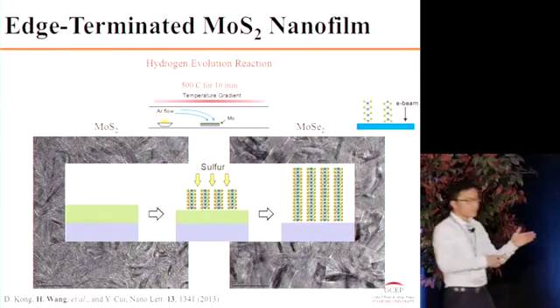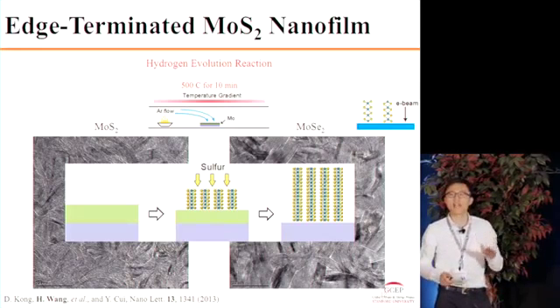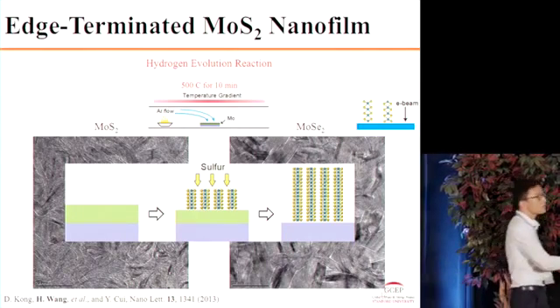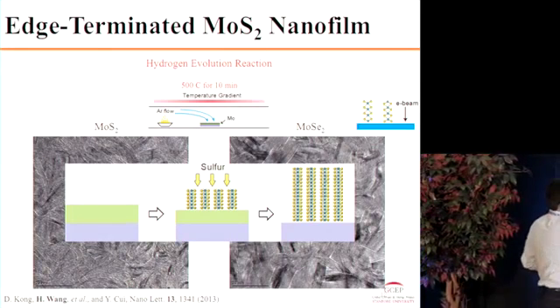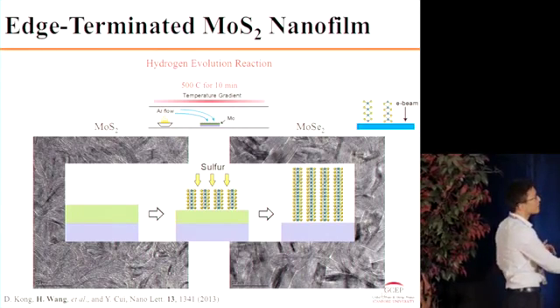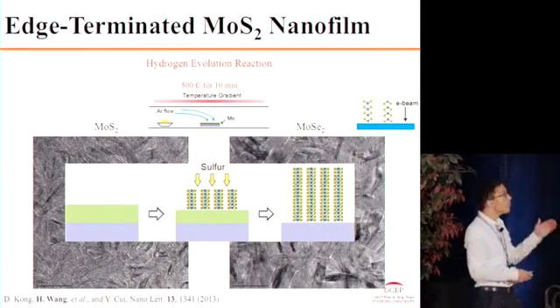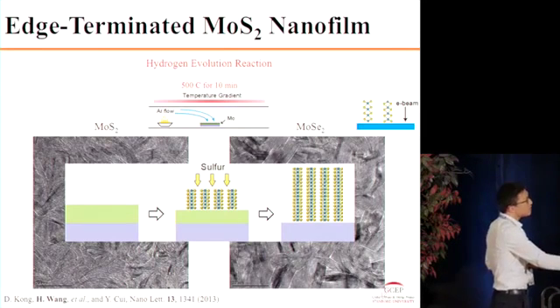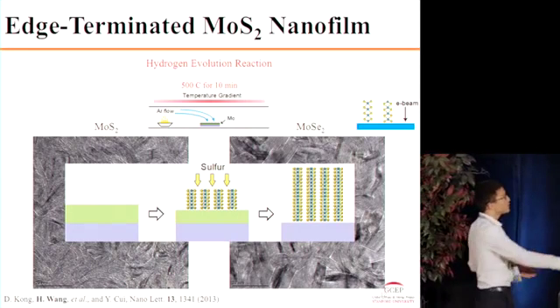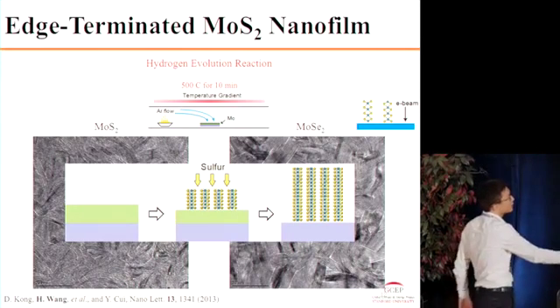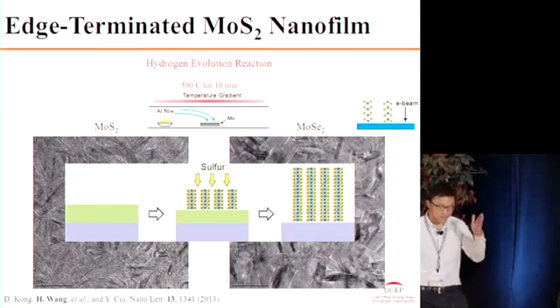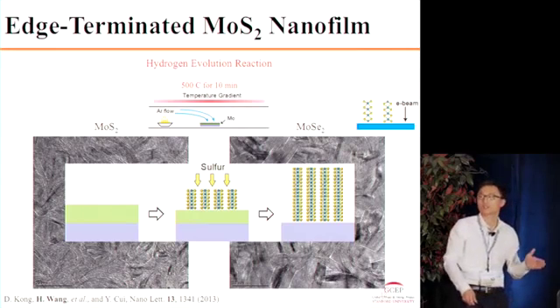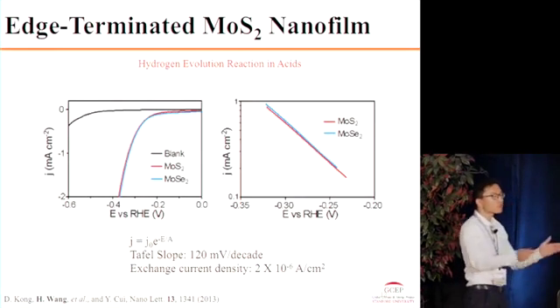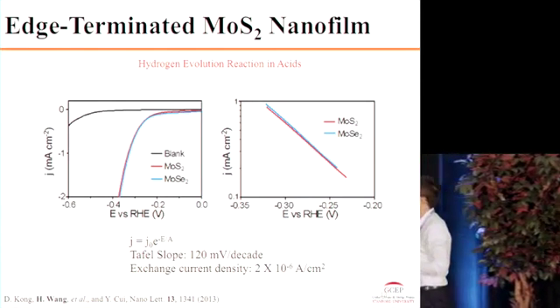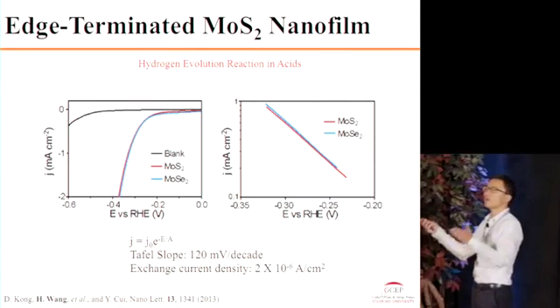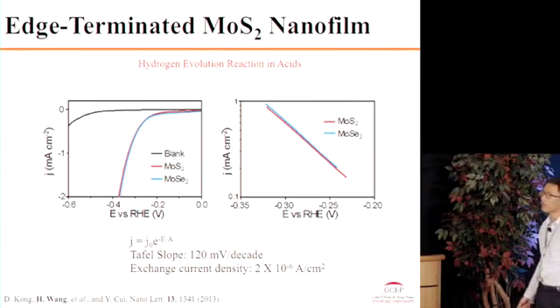People may think that the surface energy of this edge site is very high, and this structure might not be the thermodynamically stable phase for us to obtain. But the reason we can drive this reaction is that at this high temperature synthesis, the molybdenum and sulfur react so fast that the rate limiting step becomes the sulfur vapor diffusion limit. With the layers vertically standing, opening the van der Waals gap, we can have very fast diffusion of the sulfur gases through the layers, and this becomes a preferential orientation of the layers. We also tested the hydrogen evolution catalytic activity of this kind of thin film, and we can see there is still over 200 millivolts overpotential to drive this reaction.